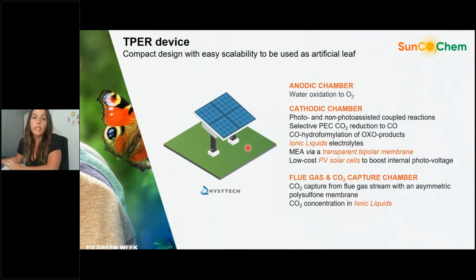In the end, we are going to integrate all those materials in a device that will integrate 3 different chambers in a single unit: an anodic chamber for water oxidation, a cathodic chamber for photo-assisted CO2 reduction to CO and tandem thermocatalytic hydroformylation to oxo products, and a flue gas CO2 capture chamber, where the flue gas from Dow is going to feed directly into this chamber to selectively capture CO2 with asymmetric polymeric membranes and ionic liquids.